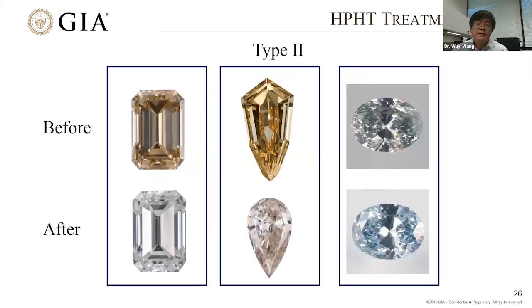So I'll show you how effective the HPHT treatment could be in changing the color of a type 2A diamond. And here I want to show you more examples of how HPHT treatment could change the color of a diamond. The top row diamond is a natural color, and the lower row is after treatment. So before and after treatment, the brown 2A turns to colorless, and sometimes brown 2A, if treated at a slightly lower temperature, could turn to pink color. And a gray type 2B diamond will turn to a beautiful blue color. The gray color will be removed.